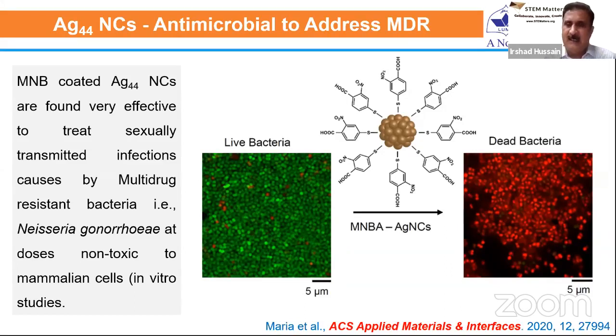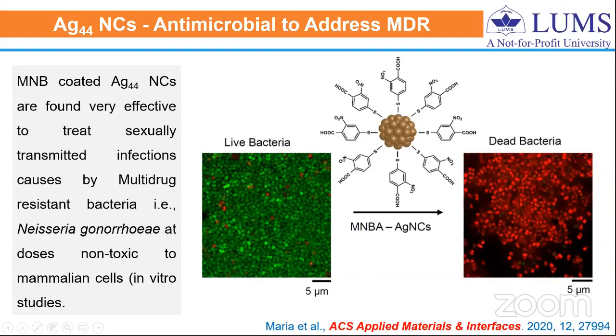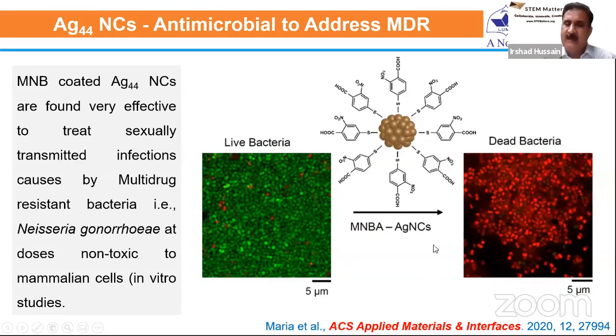And we recently tested them to kill some multi-drug resistant bacteria as well, in collaboration with Professor Antonis Kanaras at the University of Southampton. And we found that they're really very efficient at killing multi-drug resistant bacteria, that is Neisseria gonorrhoeae, which is otherwise very difficult to kill with traditional antibiotics. And the concentration that is required to kill these bacteria is not very high. At concentrations which are not toxic to mammalian cells, we were able to kill these multi-drug resistant bacteria using these silver 44 nanoclusters.